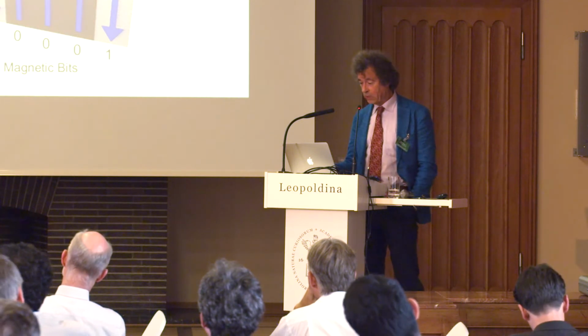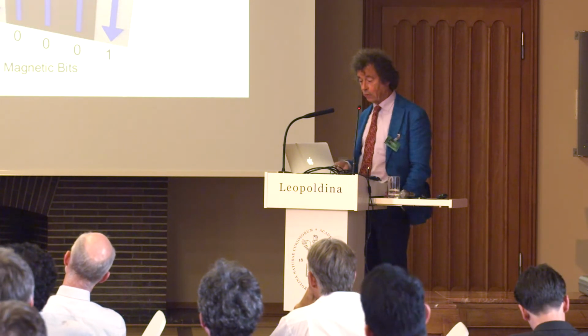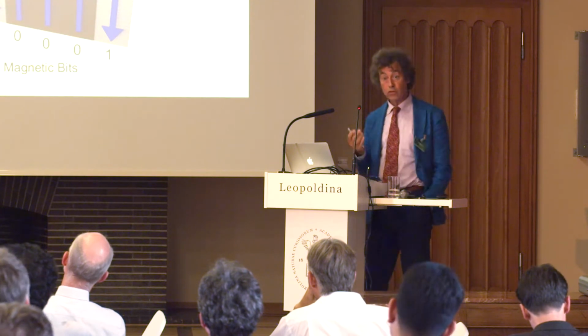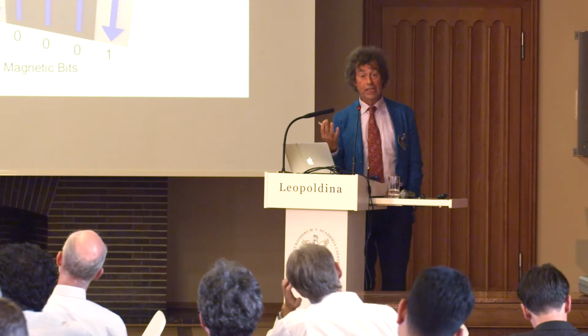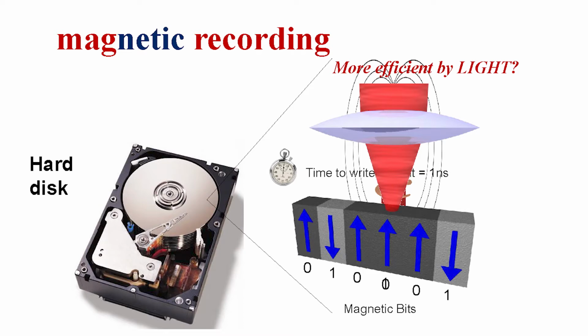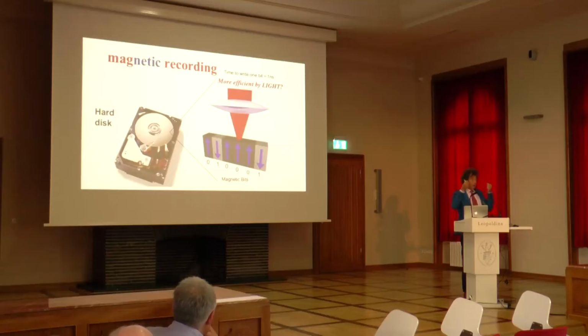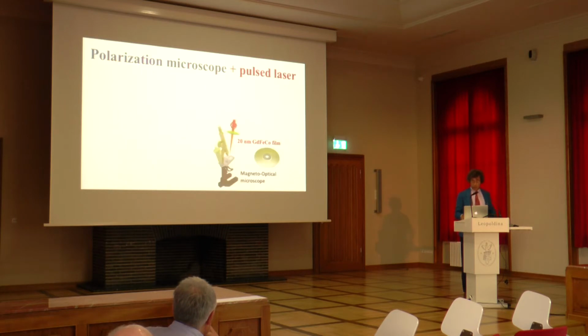And so our question some years ago was, can't we do this much faster, but also much more efficiently using light? And what light should you use then? If you want to use light and use the exchange interaction, then you want a strong pulse on the order of the time scale of the exchange interaction. And that means sub-picoseconds, femtoseconds. So this is what we started to do.